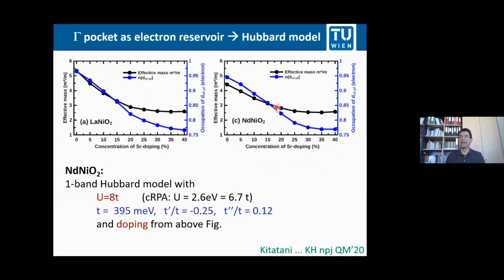Next thing to do is to really calculate the doping of our Hubbard model, or the occupation of the x squared minus y squared orbital as a function of strontium doping. And that's for lanthanum and neodymium nickelate. You see the undoped compound, because of the Gamma pocket, is a little bit doped in both cases. It's not a perfect line, but as a first approximation, you have a linear dependence. It bends off a little bit for larger dopings, but it's about 50% of the holes go into the Gamma pocket here and 50% go into the x squared minus y squared. So we end up with a one-band Hubbard model description.